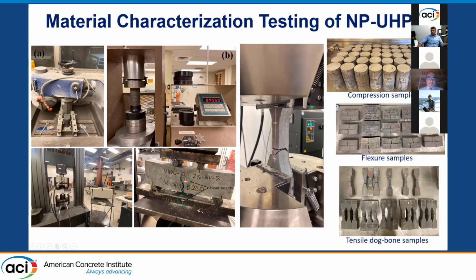So we went with the dog bone samples with a 1x1 cross section. For the standard flexure test, we did the 3x3x12, and for the compression, the 3x6 cylinders. And we wanted to do the full stress strain characterization for all these types of tests and see how this would compare to analytical equations in the literature.